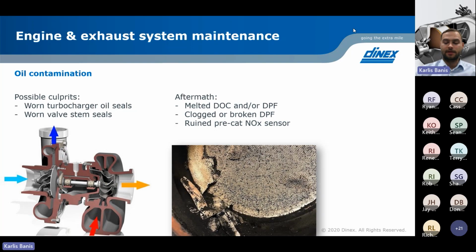And yeah, the impact on the NOx sensor is that because of the construction, it is made out of a zirconia electrolyte ceramic chip. That stuff is very porous. It actually breathes by itself. And so whatever amounts of dust or soot or other sticky substances we allow to deposit on the sensor itself, it will immediately block all of the very small pores on the sensor, and it will not allow the sensor to breathe. And as a result, it will not do any measurement. So contamination is a very, very serious issue when it comes to NOx sensors.